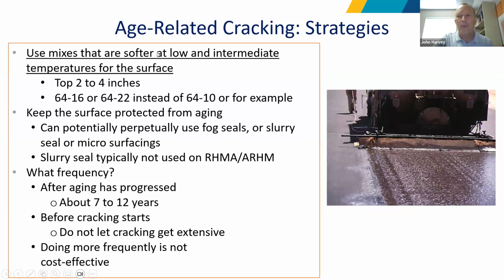So, for age-related cracking, what are the strategies? Well, the first strategy is to use mixes that are softer at low and intermediate temperature. So that sort of means around 50 to 70 degrees, and then whatever low temperature means, whatever your coldest temperatures are. We need to particularly focus on softer materials in the top 2 inches, and then we worry about it to a lesser degree down to 4 inches. And if we've got pretty good compaction, we really don't have aging below 4 inches.